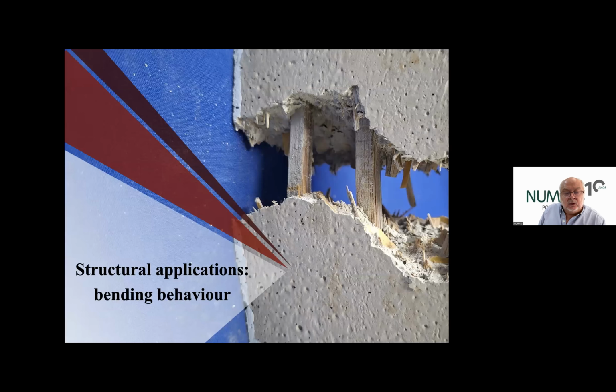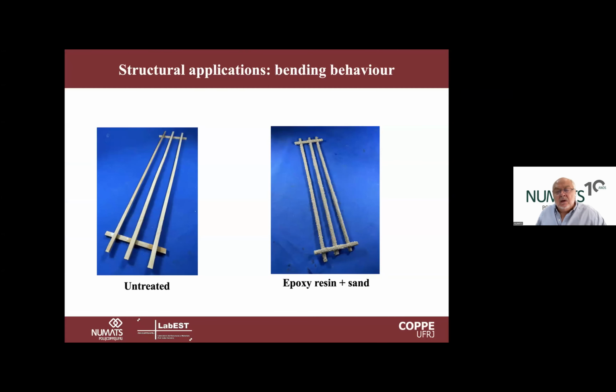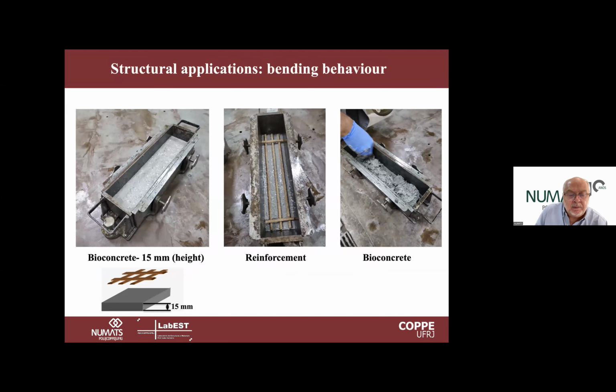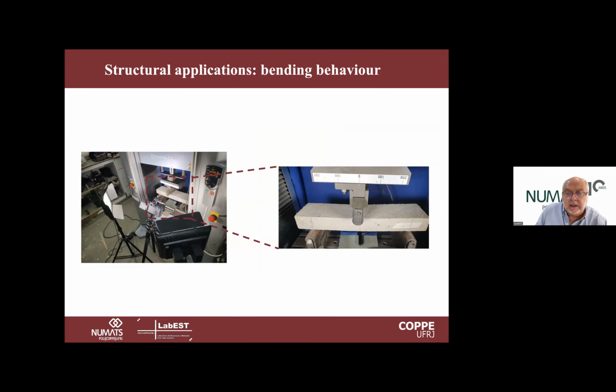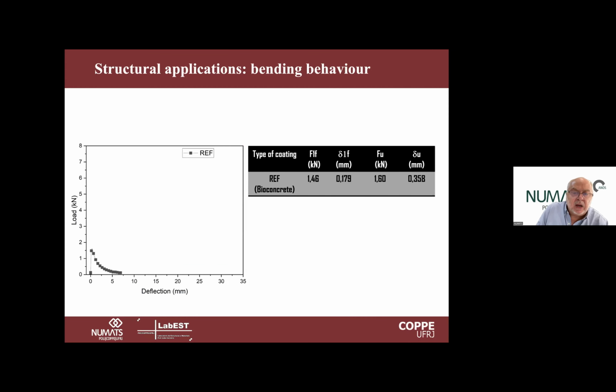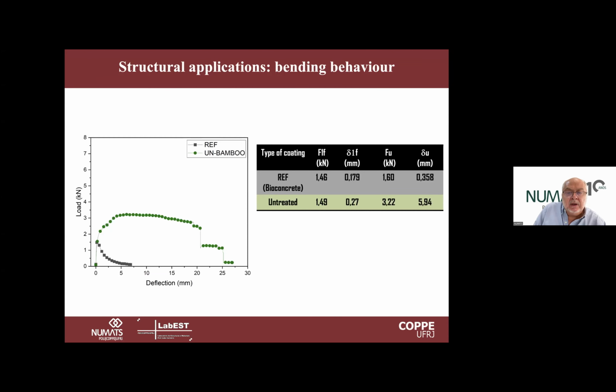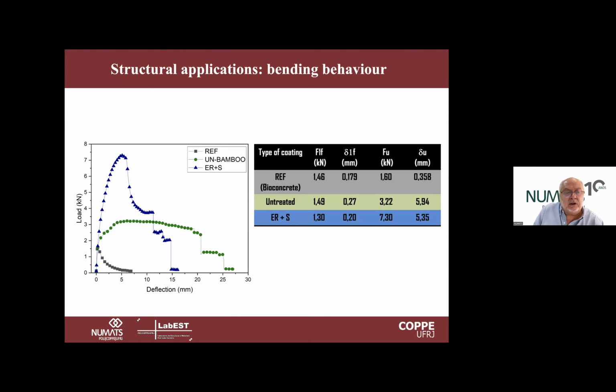So this brings us to the last part of the structural application, that is the use of untreated and treated reinforcement, now using a number of strips as reinforcement. So we put here along the height, in the back of the sample, 3 strips of bamboo, then the bioconcrete, and then we test them under bending. So we see here that when we do not have any reinforcement, so this is just the matrix, the material is quite brittle, just post-cracking failure, just the energy that is given by the small particles of bamboo. But then when we have this strip, even untreated, it can more than double and give very high energy already, but the behavior is much better when we use the treated sample.